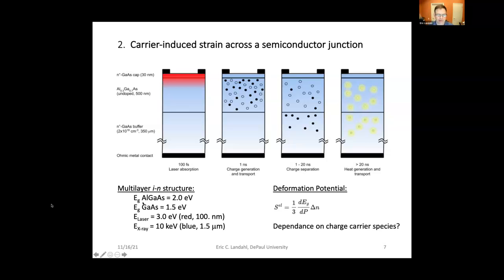So following laser absorption, one would expect the creation of electrons and holes and for them to migrate around, and then charge separation to start to set in at the junction after a few nanoseconds, with the electrons crossing into the N-doped parts of the sample and the holes staying behind along with a few electrons. These vigorously will recombine because of the high combined density, generating lots of heat in the film layer, and the charge carriers, the electrons in this case, which pass into the N-doped sample, are going to be able to move quite a significant way through this region before they start to generate heat.